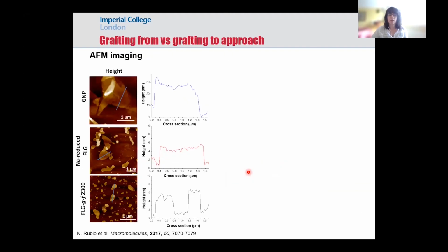We were able to characterize these functionalized graphenes using AFM. From this, if we compare the starting material to the just exfoliated and functionalized with PMMA, we observe from the AFM that the height of the starting material is around 30 nanometers for this stack of layers. And after exfoliation and functionalization, we were able to decrease this height of aggregates down to 4 to 5 nanometers.